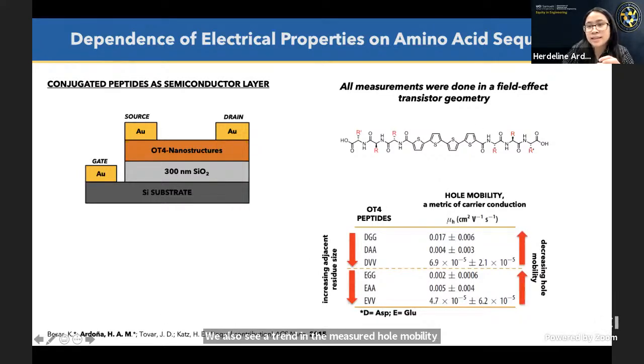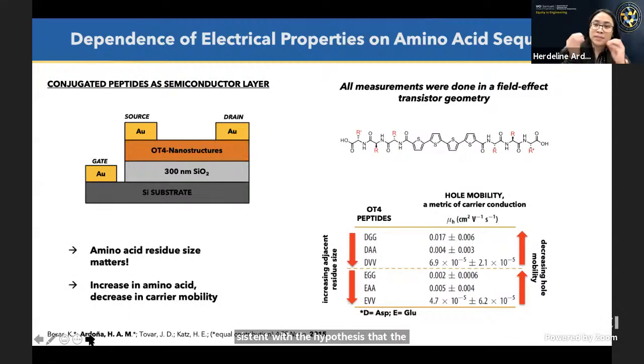and we see that those with larger amino acids next to the pi conjugated core have lower mobilities, which is consistent with the hypothesis that these minute changes in the amino acid next to the pi conjugated core definitely change the stacking distance, or at least the stacking order, and can affect the properties that I've shown you, which are the bulk mechanical properties and also the optical and electrical properties.